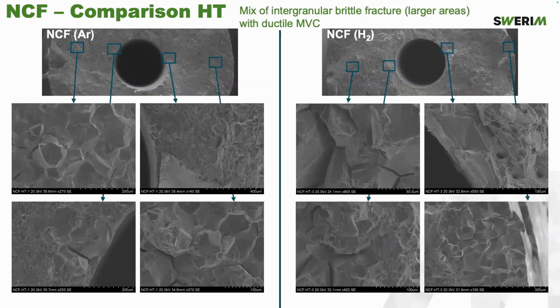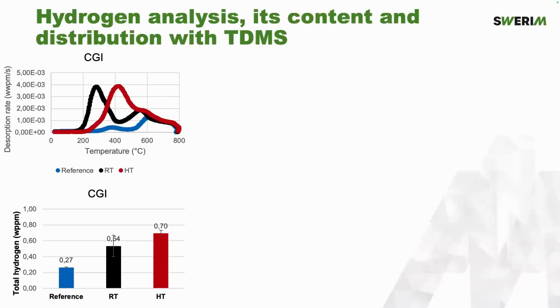High temperature, mix of intergranular type of fracture all over the surface for both type of gases, argon and hydrogen. So in principle, this is probably typical mechanism at elevated temperature. It's not really related to hydrogen. And also some ductile areas. Digging into the hydrogen effect.